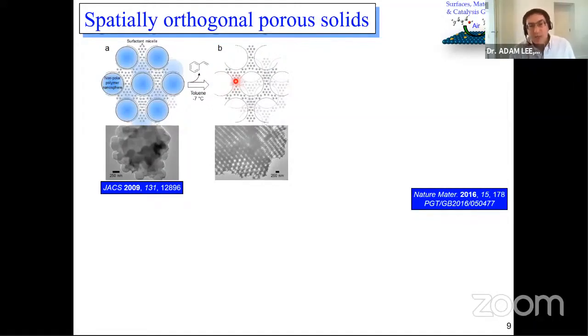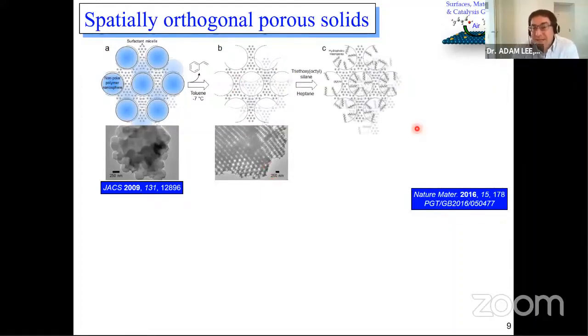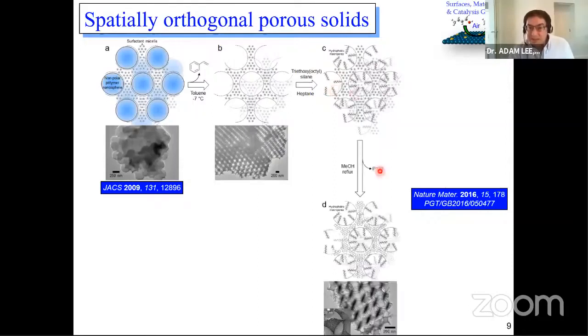Why is that useful? It's useful because these macropores can now have their surface functionalized selectively. So we can introduce, for example, an octyl group to make these macropores hydrophobic. We can then take out the template that's inside the mesopores using methanol. We take out the P123, and we now have a completely empty architecture.